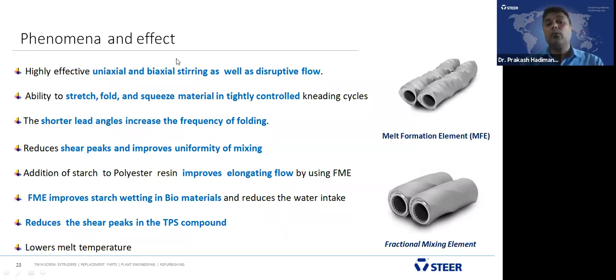I will explain the phenomena and the effect of using these two elements of FGT technology. One is a melt formation element, second is fractional mixing elements. The melt formation element provides highly effective uniaxial and biaxial stirring as well as disruptive flow into the PBAT and the starch, and the ability to stretch, fold, and squeeze the material in a tightly controlled kneading cycle. The melt formation element does that. And it has a shorter lead angle to increase the frequency of the folding. Shorter lead helps to increase the frequency of the folding and elongation. It also reduces the peak shear and improves the uniformity of the mixing in the PBAT and starch.